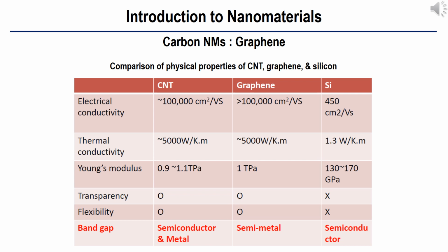Graphene is the most reactive form among all the carbon allotropes. This reactivity is partially attributed to the large fraction of edge carbon atoms which are typically thermodynamically less stable than the carbon atoms in the honeycomb lattice. It makes graphene easily suffer oxidation at relatively low temperatures such as 350 degrees Celsius. Graphene can be modified with oxygen and nitrogen.